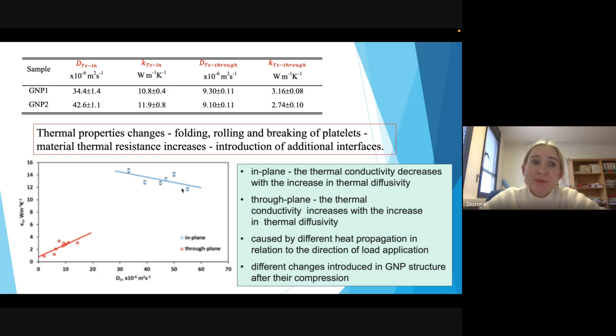So the thermal properties generally decrease, but the pressure is applied in the direction perpendicular to the sample surface, so the changes in-plane and through-plane are different, and the heat also propagates differently in both these directions, which results in different behavior of the thermal properties. So that was the very basic application of the beam deflection spectrometry.